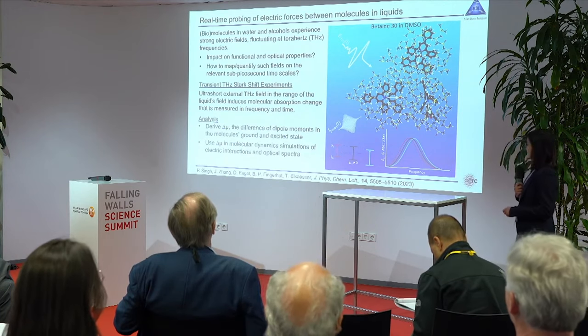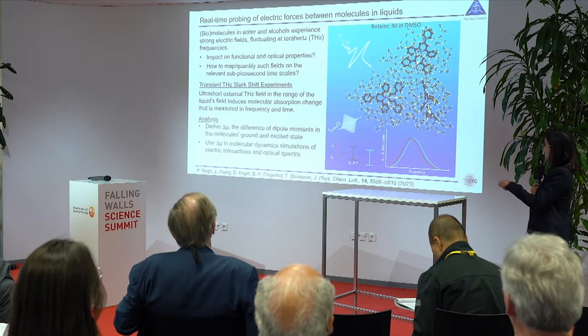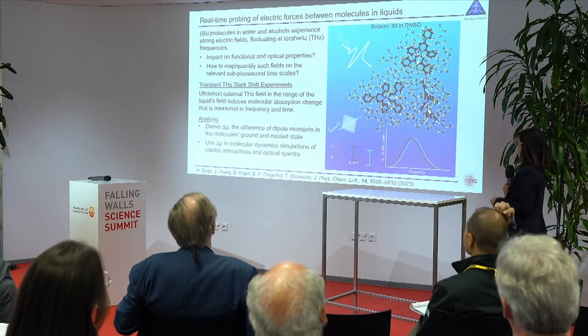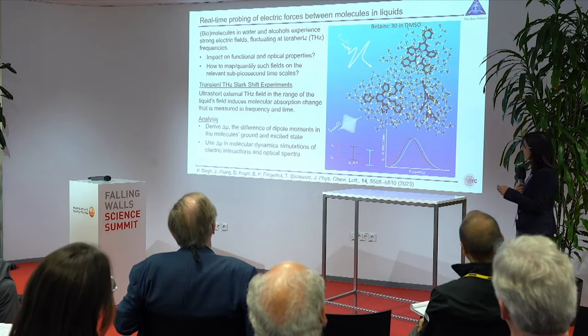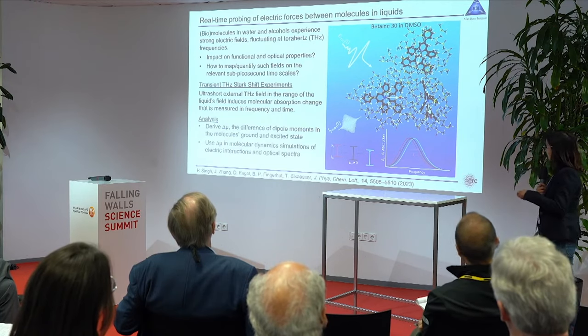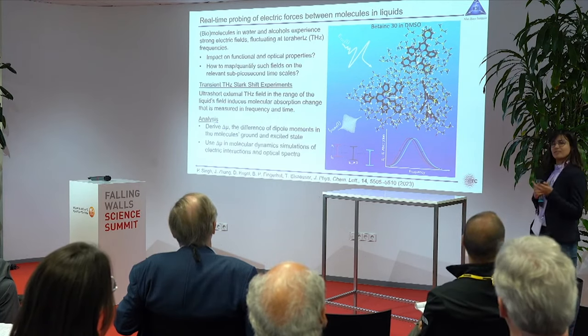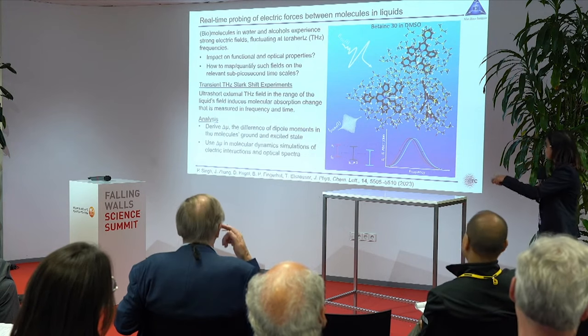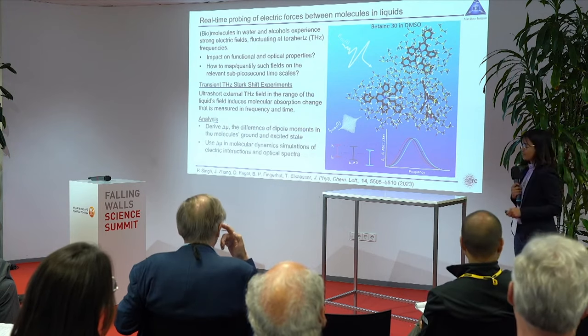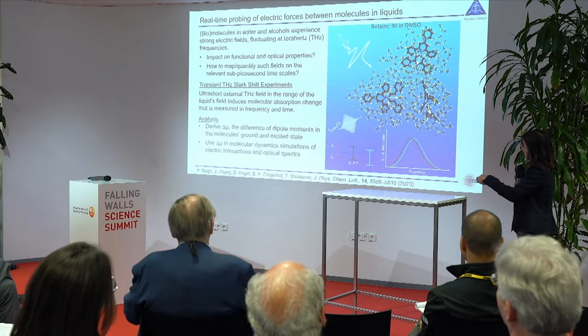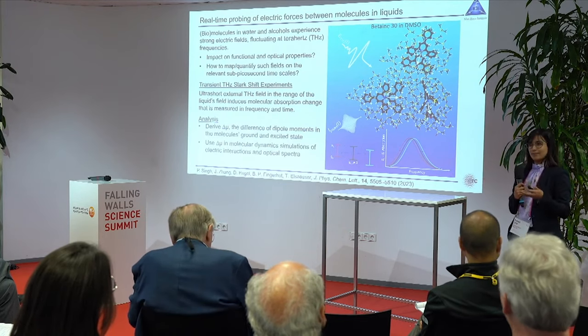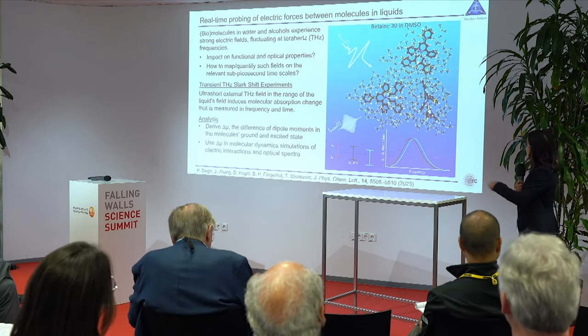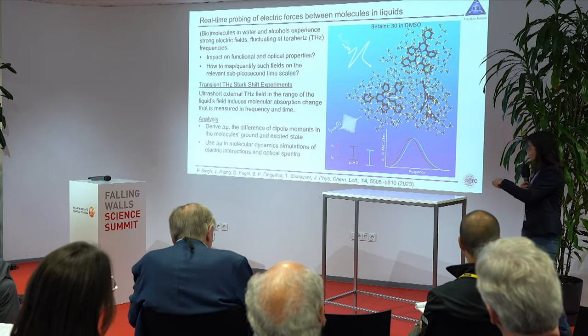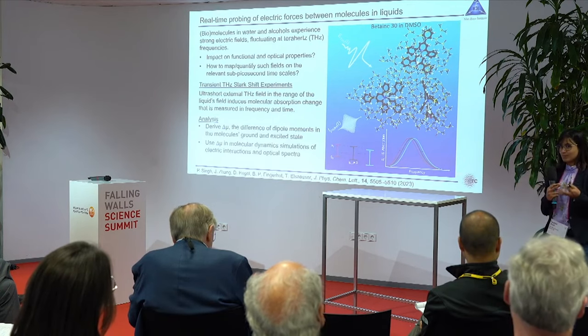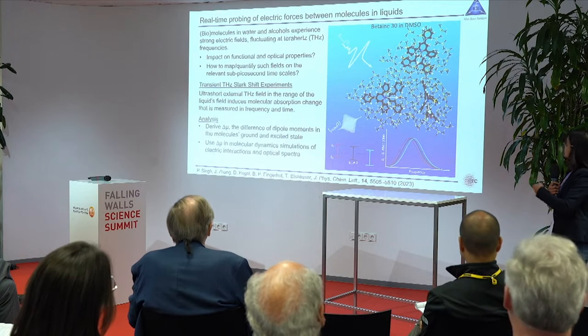In our experiments, we make use of the electronic absorption spectrum of the chromophore. In the presence of an external electric field, this absorption spectrum shifts, and the shifts can be visualized as shifts of the transition energy levels of this chromophore. The transition energy level shifts are proportional to the dipole moment of the chromophore. So by mapping the spectral shifts, we can learn something about the dipole difference of these chromophores in the two states.